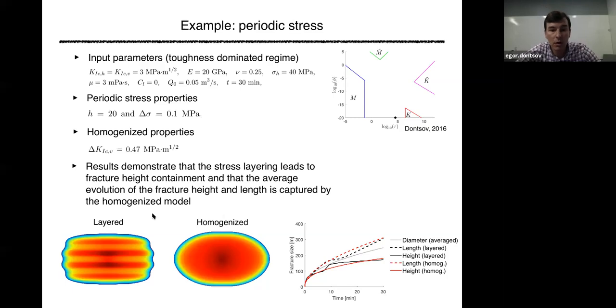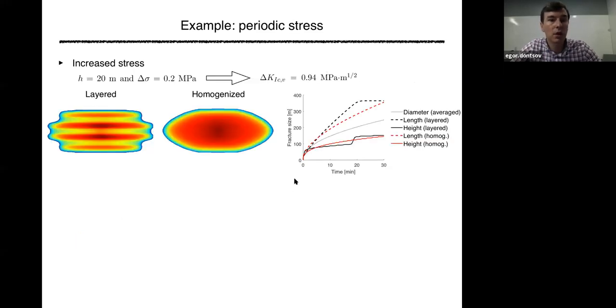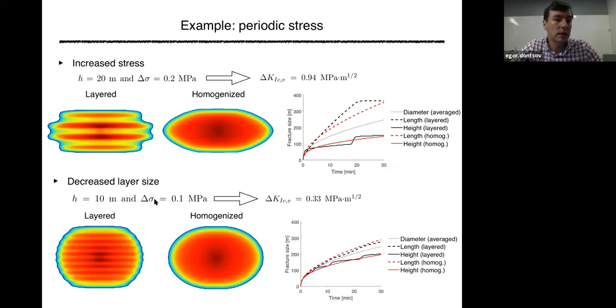And again, as before, we have layered and homogenized. If you use this value of toughness and add it to the other properties, we capture the aspect ratio and evolution of height and length accurately. And of course, we can do different contrast, same layer. Now we have more effective toughness, and if you change the layer size, going from 20 to 10 meters, because this is layer size dependent, now we have less toughness, and again, we capture the behavior very well.